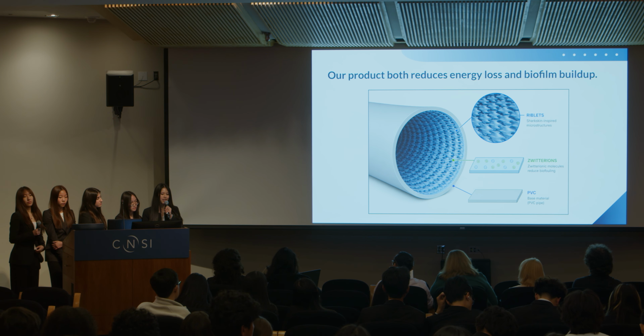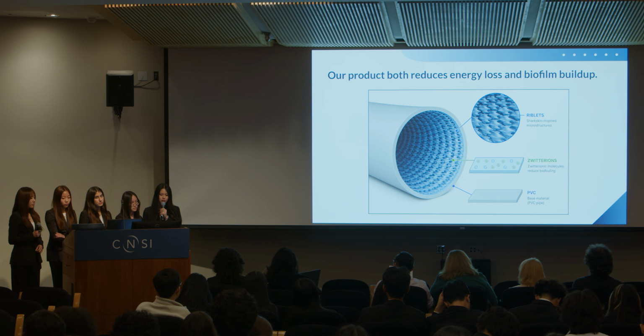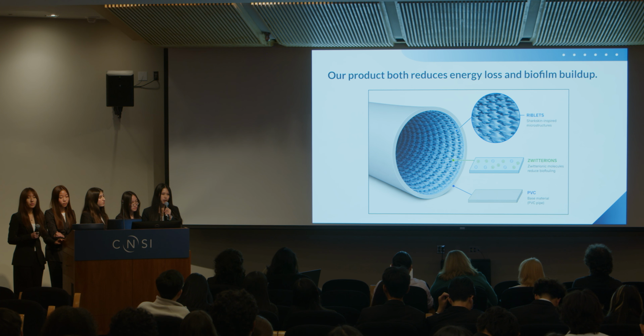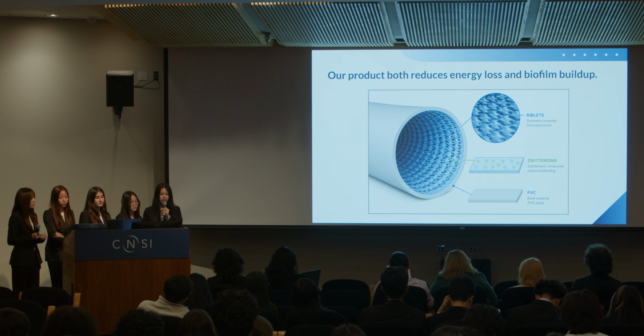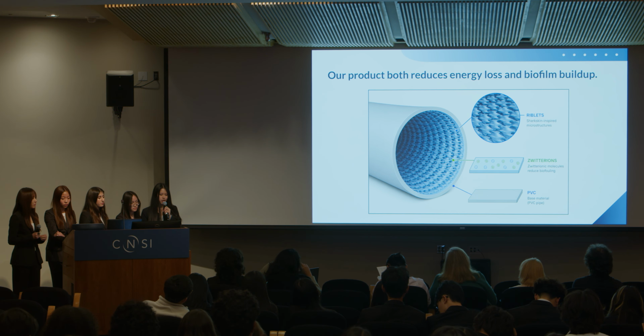In addition to these riblets, SharkPipe incorporates Zwitterionic polymer technology directly into the pipe material rather than relying on a temporary surface coating. During production, these amphiphilic molecules naturally migrate toward the pipe's inner surface, forming a thin nanoscale hydration layer that strongly binds water molecules. Research has shown that this hydration barrier can cause a 90% reduction in bacterial adhesion.